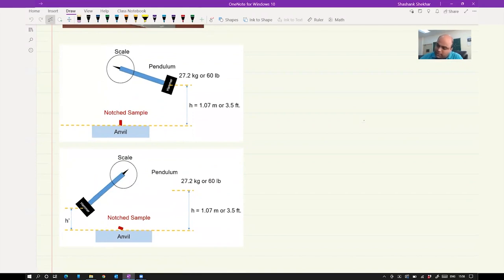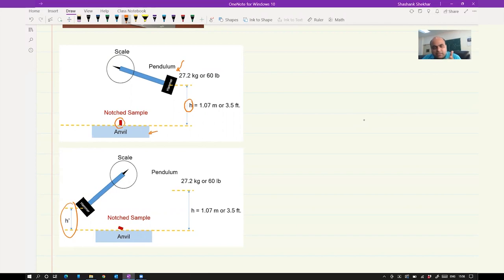Here I have shown another schematic. You have a pendulum or hammer and a sample placed on the anvil. You release the hammer — it strikes the sample, and then achieves a different height h'. Initially the hammer height was h; after fracturing the sample the height is h'. Note that h' is less than h, meaning some energy has been lost. Some is lost to air friction, but some is imparted to the sample, leading to fracture.